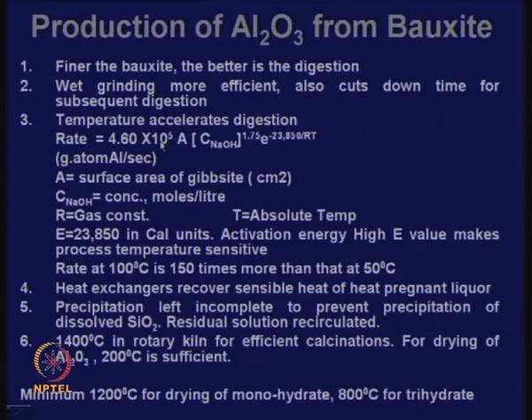Here is an equation that has been developed, approximate equation. The rate depends on concentration of sodium hydroxide, obviously. The stronger the sodium hydroxide concentration, more is the rate. And here it depends on temperature. If temperature is higher, this will be more, so this will be less, so this will be more. Now, this is the activation energy, and this activation energy is supposed to be very high actually, which means it is very highly temperature dependent. It is also dependent on surface area of gibbsite, that is why it is called A, means if you grind it more, then rate will be more.